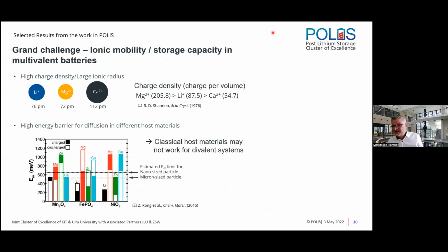Okay, then another challenge, and everybody knows that who's working in this field with multivalent systems. A grand challenge is the ionic mobility of these ions. And this is something which heavily affects the storage capacity of multivalent batteries. Here you have some examples, and the people who did modeling in this field came out with energy barriers for the hopping of these ions in the material, which are quite high and mostly unacceptable. You won't end up with a well-working system if you have energy barriers beyond 500-600 milli-eV. So this is leading to nothing.